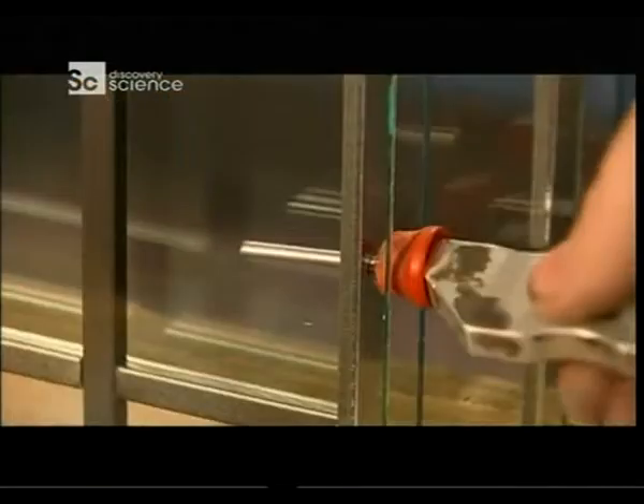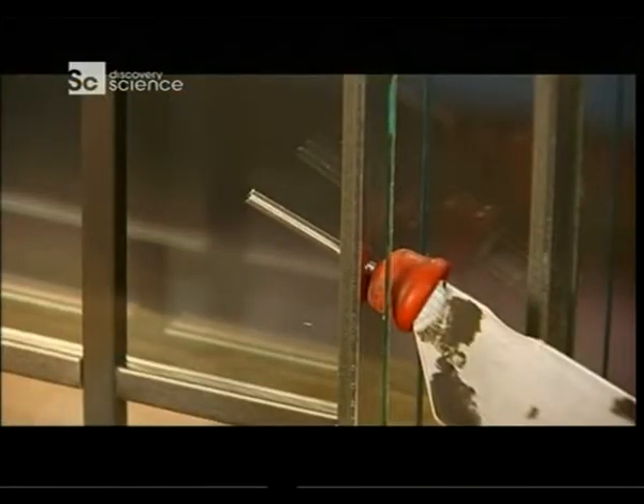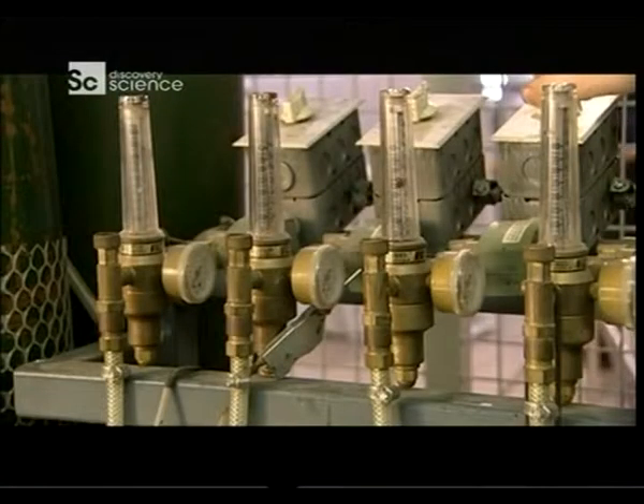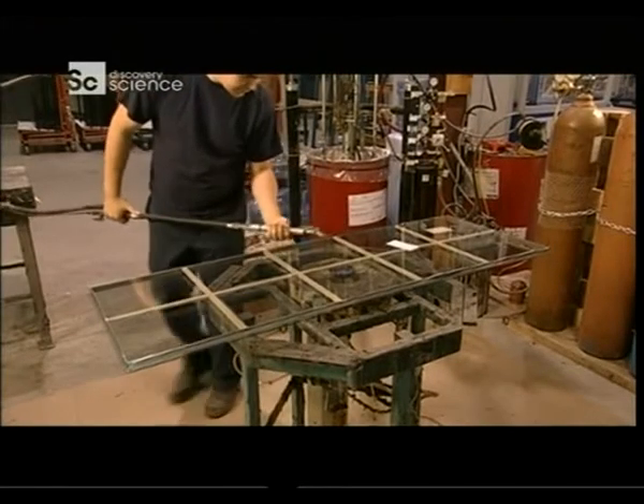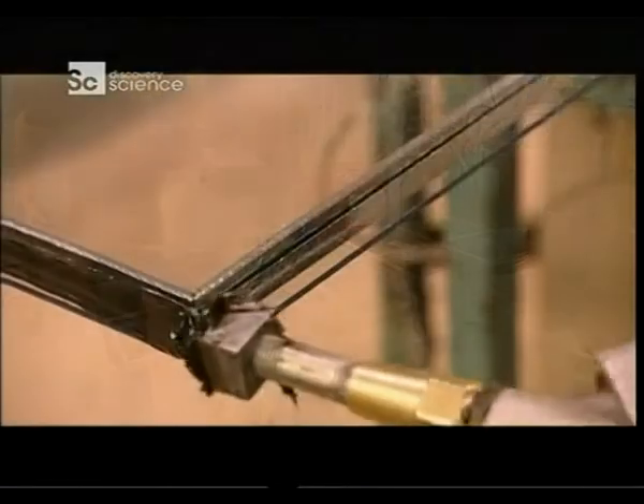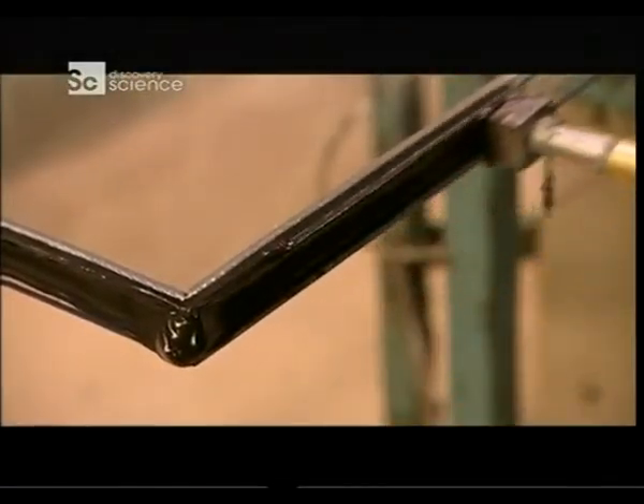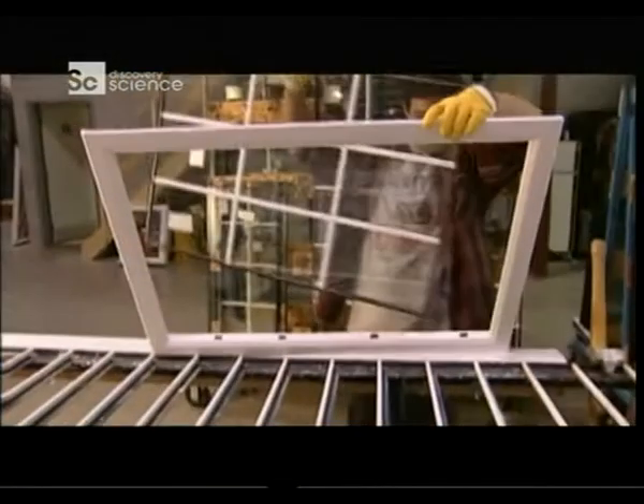to the spacer. After the glass exits the press, argon gas is pumped through the hole at the bottom of the spacer. The speed of the gas flow is critical. If it's pumped too fast, it'll mix with the air in between the panes, rather than push it through the hole at the top of the spacer. After plugging the holes, the spacer is coated in polyurethane sealant. This makes the thermopane completely airtight. Now it's ready to go in the sash.